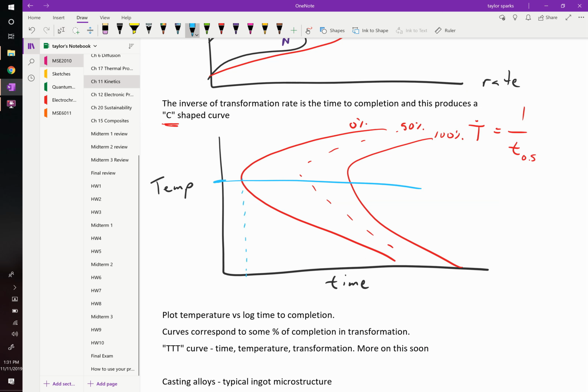Why do we care about this? Because think what this lets us do now. Up here, we had our temperature at T alpha beta. If you cool down from T alpha beta sufficiently fast, say at that rate, where time is changing but you drop that temperature really fast, you never touch that line. We call that the nose of the TTT curve, because it looks like a nose sticking out. If you never touch that nose of the TTT curve, then you don't get transformation.